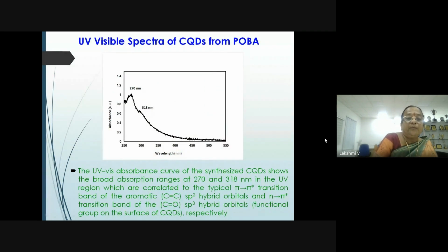And further investigation using UV visible spectra of CQDs from POBA. The UV visible absorbance curve of the synthesized CQD shows broad absorption ranges at 270 and 318 nanometer in the UV region, which are correlated to the typical pi to pi star transition band of the aromatic C double bond C sp2 hybridized orbitals and n to pi star transition band of the carbonyl group and sp3 hybridized orbitals for any functional group on the surface of CQDs, respectively.